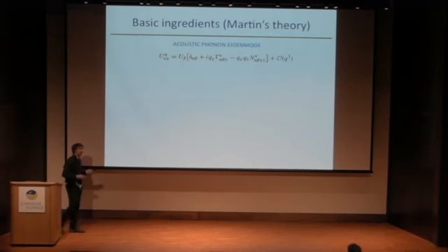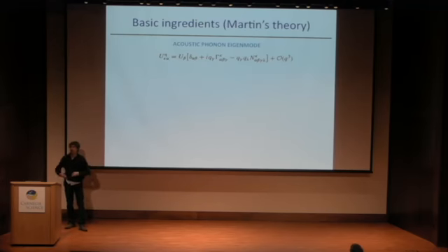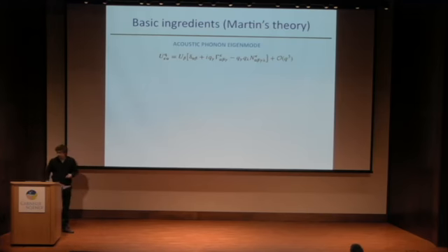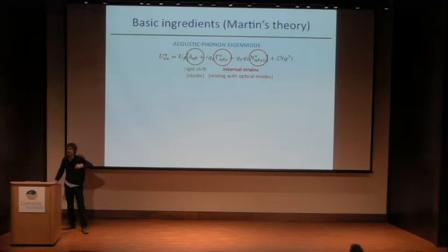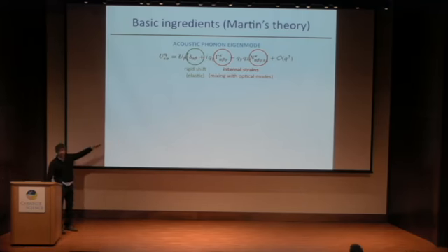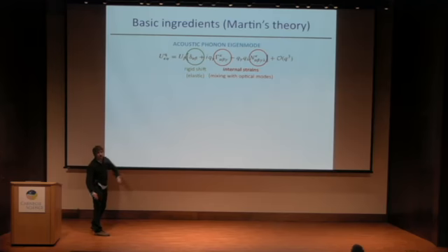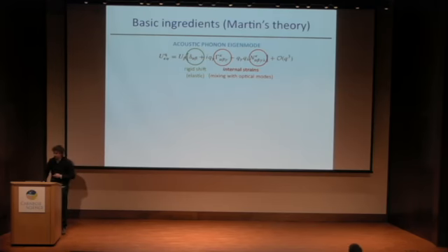What are these properties? What do we need to calculate the flexoelectric response? Well, the first thing is the acoustic phonon eigenmode, so the atomic displacements that are associated to the acoustic phonon. Of course, these displacements are trivial if you consider only the gamma point, but if you move away from the gamma point, the acoustic phonon increasingly mix with the optical modes, and you have these so-called internal strain tensors, which relate at first order in Q to piezoelectricity, and at second order in Q to lattice-mediated flexoelectricity.